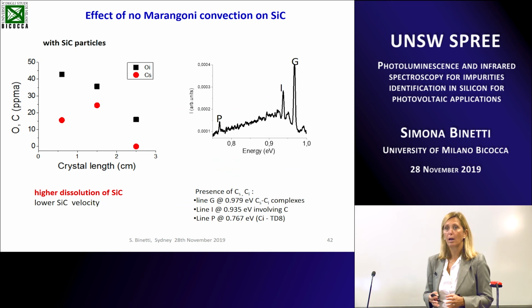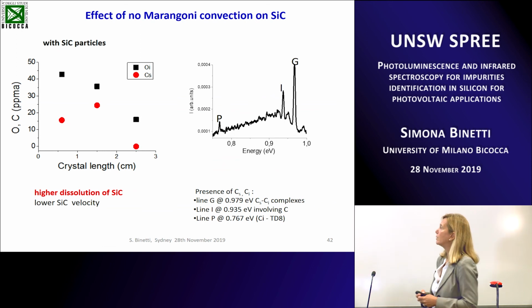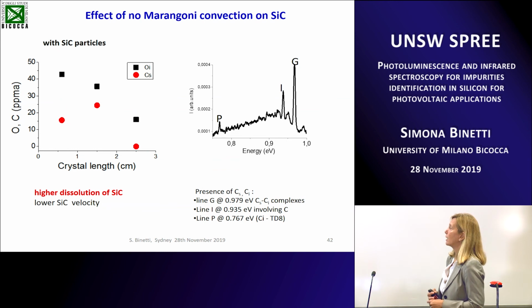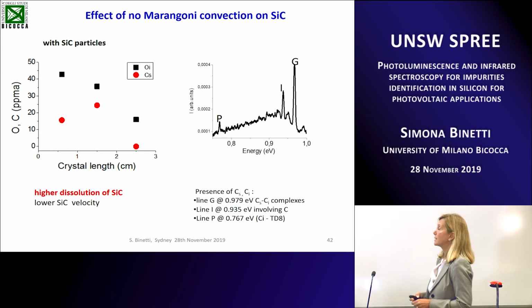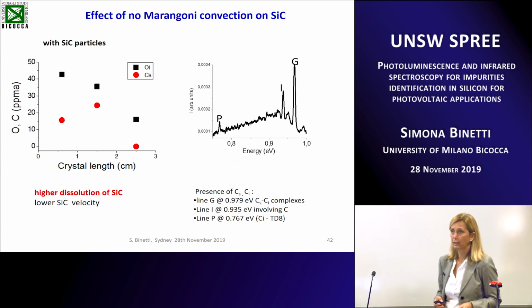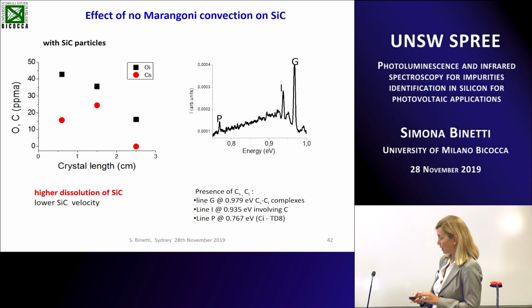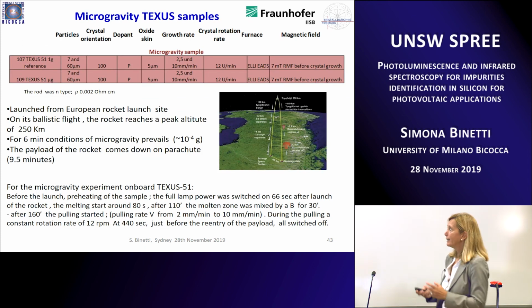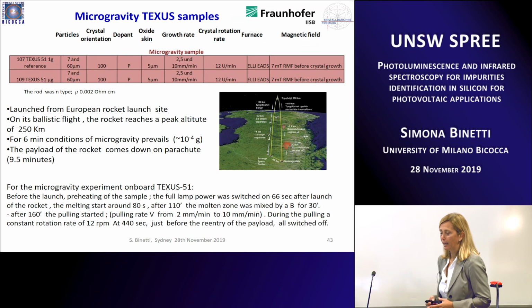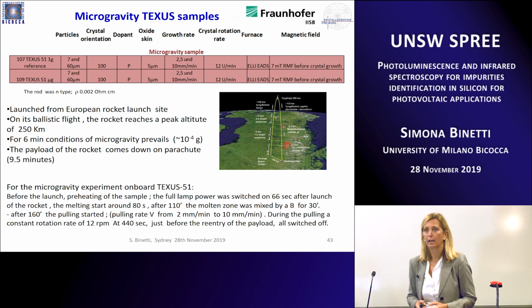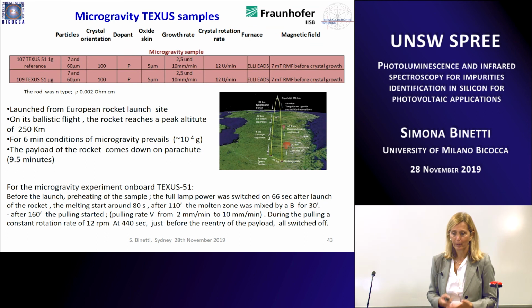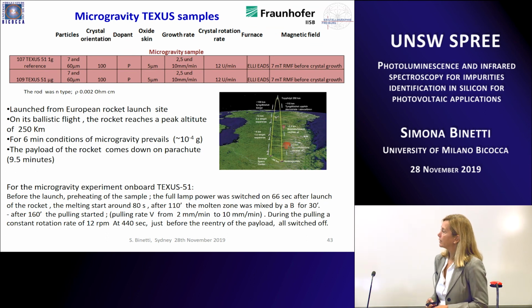co-presence of oxygen and carbon can enhance the oxygen precipitation, the co-precipitation. It's a whole work that is based on the fact that we have a combination of an injection of interstitials and vacancies, and by photoluminescence, as expected in this sample, we detected all the lines related to carbon-related defects. So the I line, the G line, and also the P line, because we have nano-precipitate thermal donors of silicon. Then finally we succeeded in having a real float zone ingot grown in microgravity condition with 10 minus 4 g.